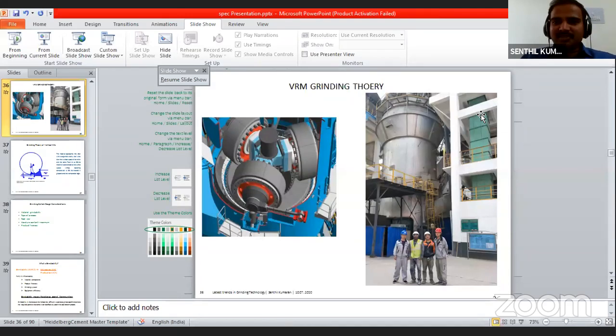So we test the material basically. For example, if it is limestone grinding, the limestone will have a certain grindability. We test this grindability and we know the value. So we don't need that much impact force in the system. When we have the 90 mm media, if it keeps on hitting, only the impact will be there. The attrition will not be there. So through the proper size distribution of the media, for example, normally I would like to add 23% of the 90 mm, and then 32% of the 70 mm, and then the percentage will be like that. So the proper grinding media size distribution plays a major role in controlling the grinding heat losses, and also the material.